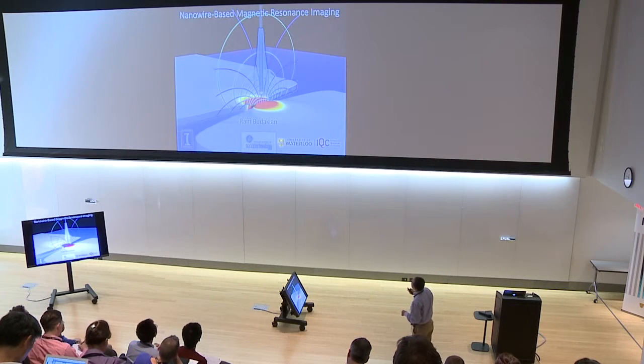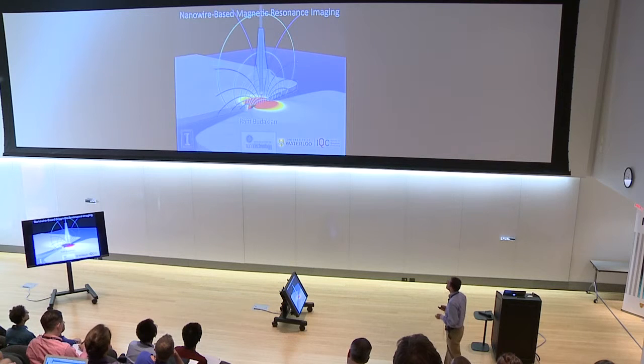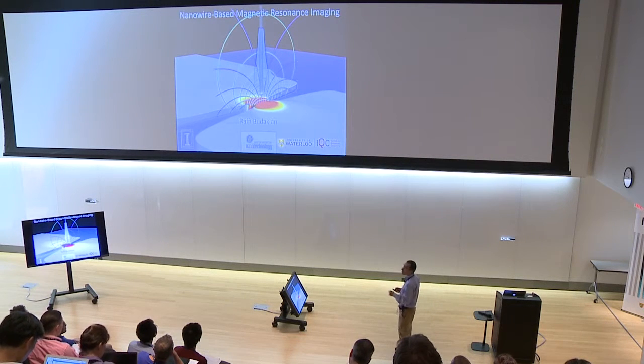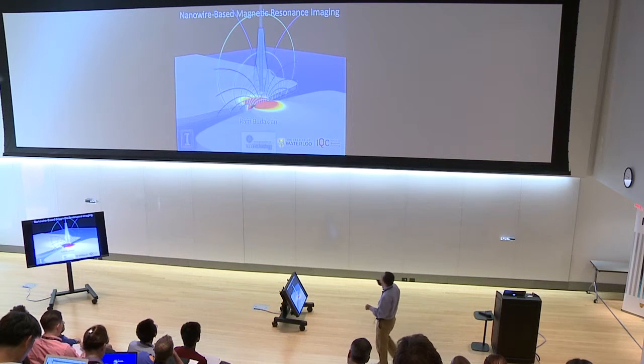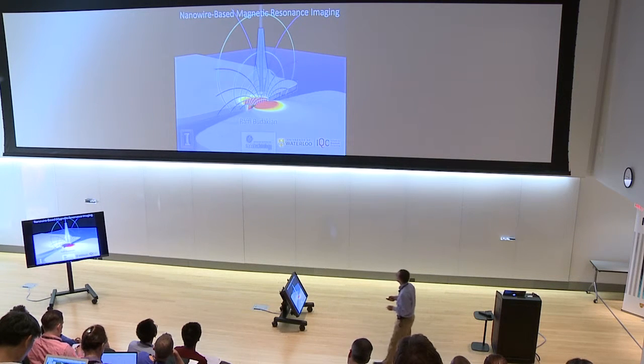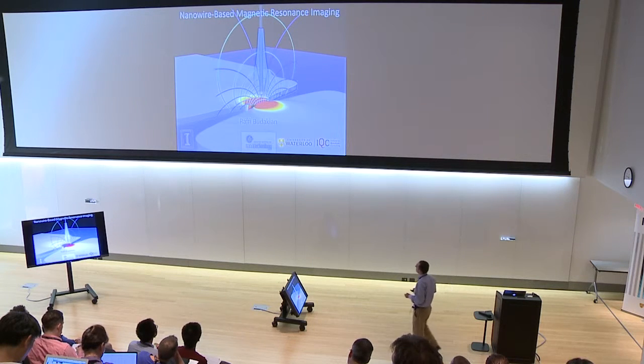Let me explain this picture. This is a nanowire mechanical resonator, a single crystal silicon nanowire between 50 and 100 nanometers in diameter, about 20 microns long. This is a constriction patterned in a silver film, about 100 to 200 nanometers across. We pulse very intense currents through this constriction which generate magnetic fields that allow us to do magnetic resonance, imaging, and readout to couple the spins to the nanomechanical oscillator.